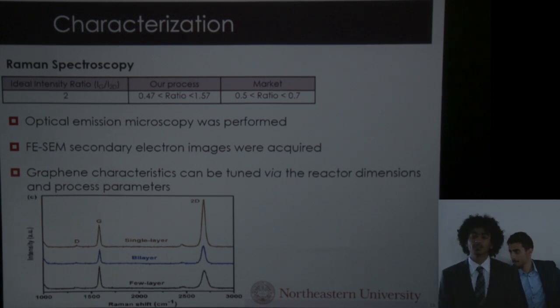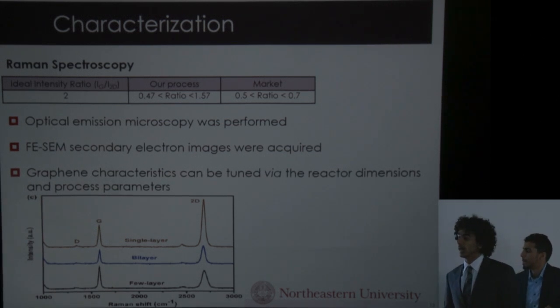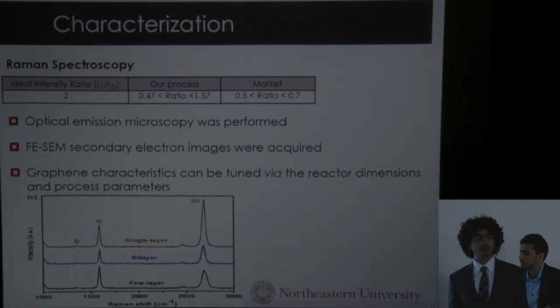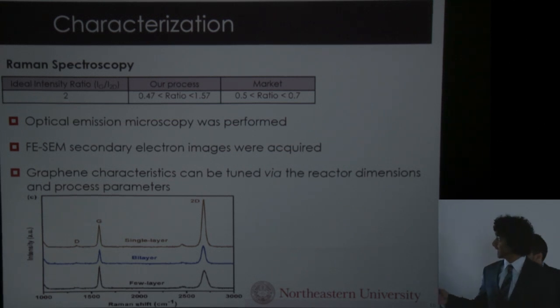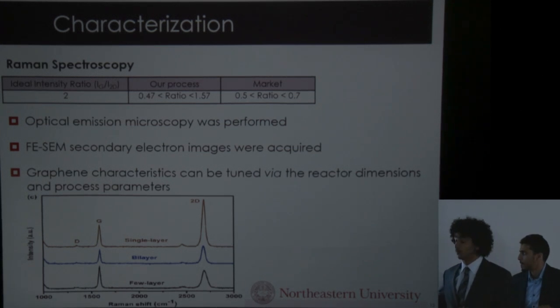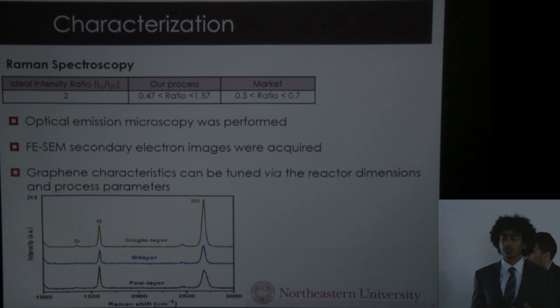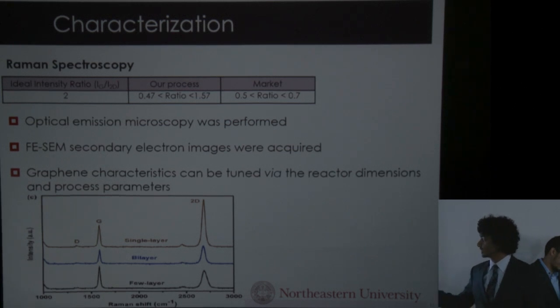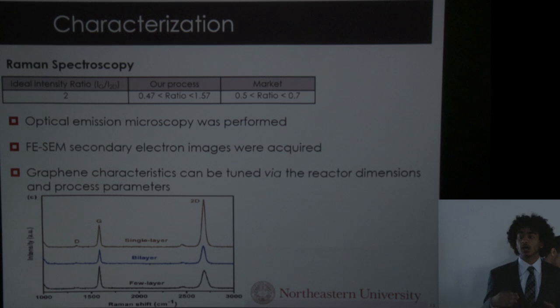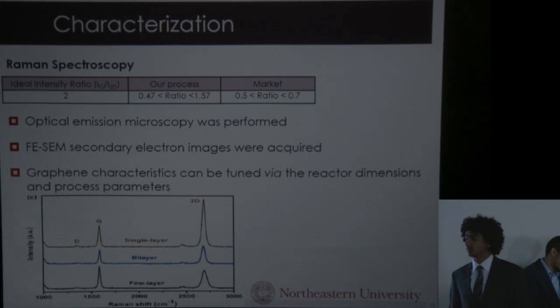A perfectly deposited graphene layer consists of a number of carbon atoms. Each carbon atom is connected to 3 other carbon atoms. This structure will allow for the 4th valence electron of carbon to be there for conduction, and it showed an ideal Ig to I2D ratio of 2. Through our process, we were able to get to an Ig to I2D ratio of 1.57, whereas the current products provided in the market have a ratio of 0.7. We also use an FE-SEM secondary electron imaging to make sure that we have a better quality product.